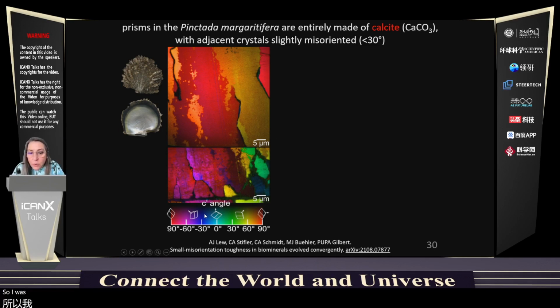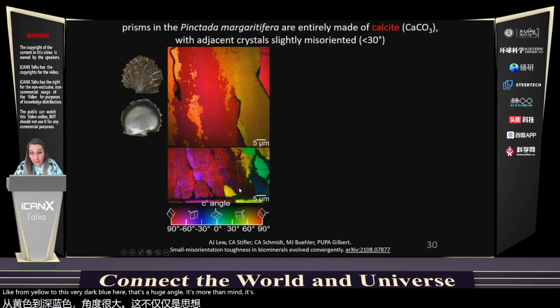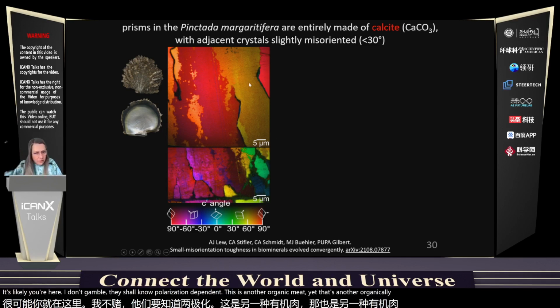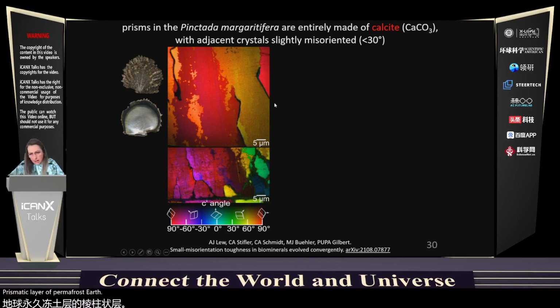So I was saying, even when the angles change a lot, like from yellow to this very dark blue here, that's a huge angle. It's more than 90-degree variation. Then you always find this black layer in between. These black layers here are organic. They show no polarization dependence. This is another organic layer. That's another organic layer, which are very well known to exist in the prismatic layer of pearl oysters and any other shell, in fact. Wherever the misorientation is large, then the organism puts a thick organic layer.